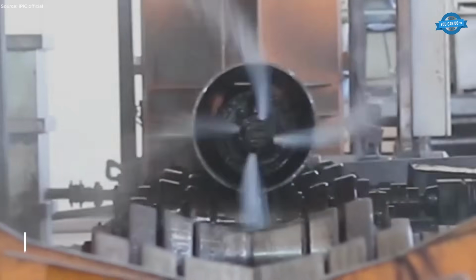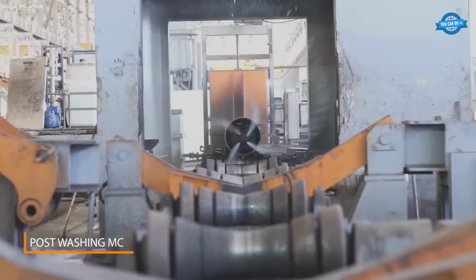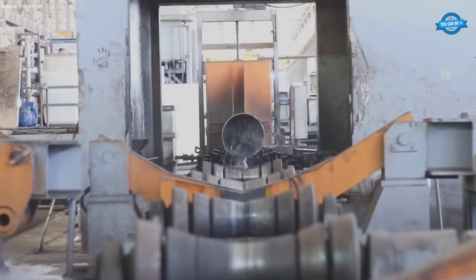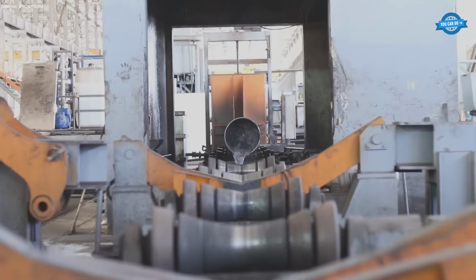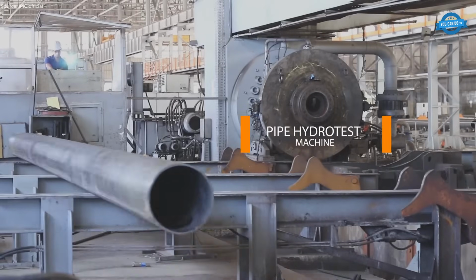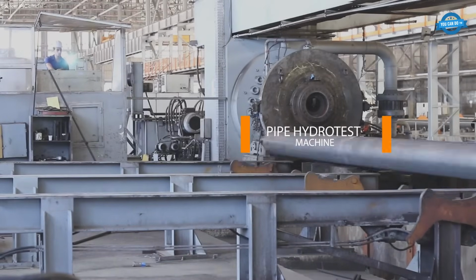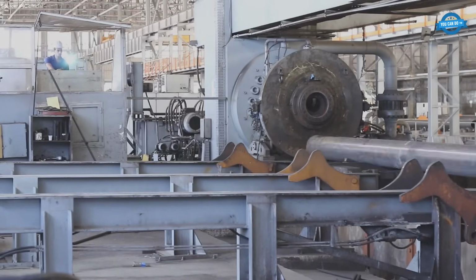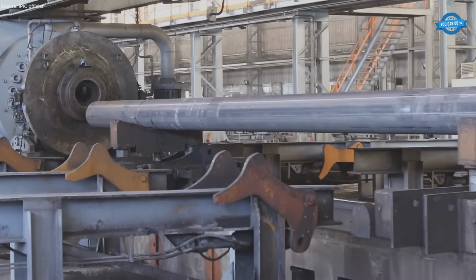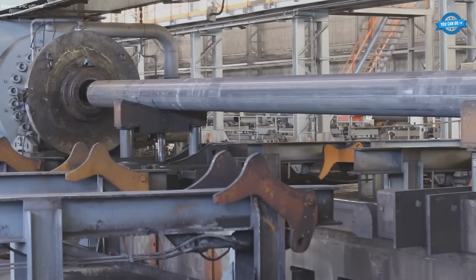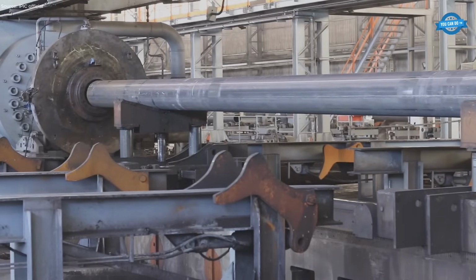The pipe must then prove its ability to withstand operating conditions through a hydrostatic test. In this process, water pressure is applied internally to confirm the strength of the welds and the overall pipe body. Advanced, non-destructive evaluation follows, using ultrasonic weld detection technology to identify any hidden defects along the weld seam.